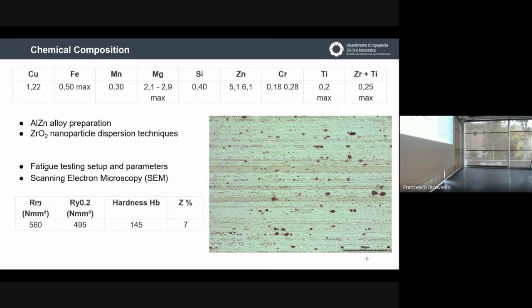But now, this is as-received material. You can see that the microstructure is characterized by an oriented structure, without heat treatment. So this is the chemical composition. You can see that we use the traditional 7000 alloy with zinc, copper, and magnesium, and the resistance is very high. It's comparable with the resistance of the steel tube.